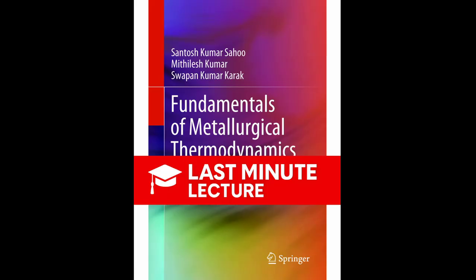The key piece of information you need here is delta V, the change in volume during the reaction. For reactions involving only solids and liquids, delta V is often tiny. It's negligible, meaning pressure has very little impact on delta G. But if you're dealing with a reaction that involves a gas phase, like reducing iron ore in a blast furnace or synthesizing compounds at extremely high pressures, the volume change is significant, and that pressure integral becomes a dominating factor. You have to know the volume change precisely.